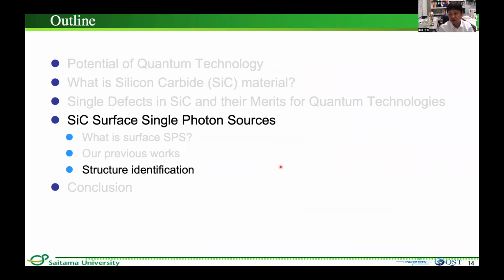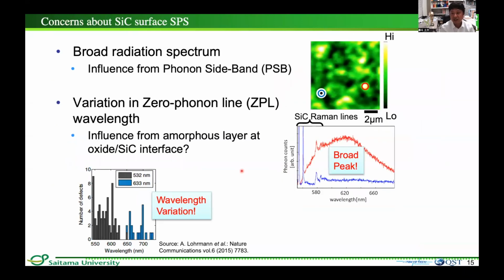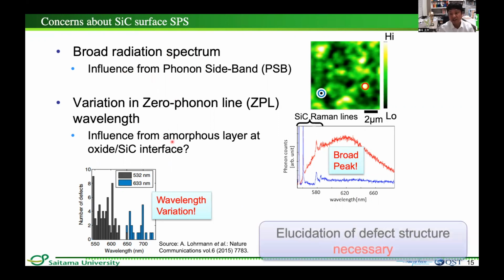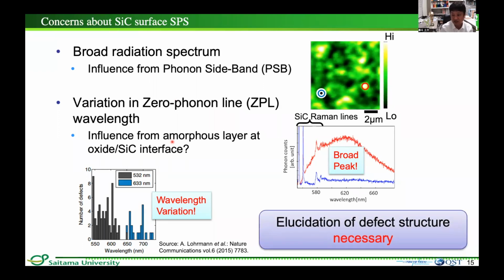Next, I'll switch to studies on structure identification of the surface SPS. Although the surface SPS exhibits good properties such as high bright emission and room temperature electroluminescence, there are some problems to solve before practical use of them. One is that their radiation spectra are generally broad, which is influenced from a phonon sideband. Another one is variation in radiation wavelengths of each SPS, which is probably due to the influence from the amorphous layer at the oxide silicon carbide interface. Anyway, it is very important to elucidate the defect structure of the surface SPS.